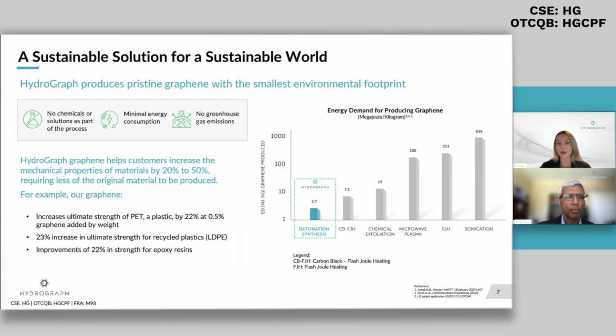If you look at the chart to your right, you can see that our detonation synthesis has by far the lowest energy demand. When you look at competitor processes, you'll look at chemical exfoliation and microwave plasma as two of the dominant forms. Not only is our production process a strong ESG play, but also using the end material is very good for